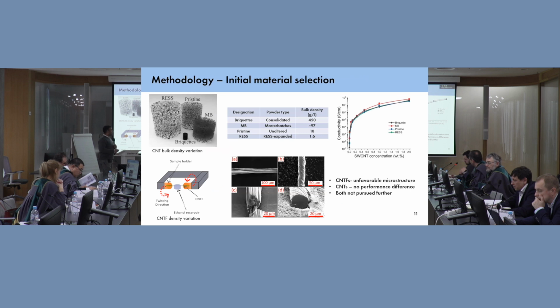Right here. Yeah. So we went with higher ones in this case. Of course, with very low ones we can get percolation. It's very possible to achieve this. However, we notice that the spread is quite large, and this is because when you're near percolation, it's very difficult to control the development of the percolation network. In this case, you have ohmic contacts, you have tunneling contacts, but you cannot really control what the distribution of both of them is.